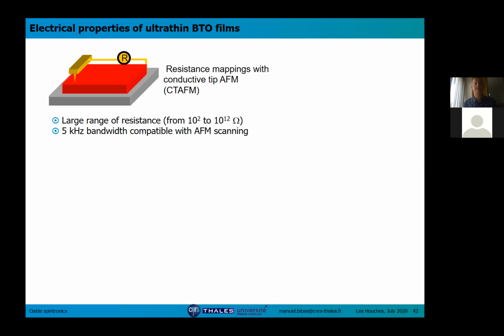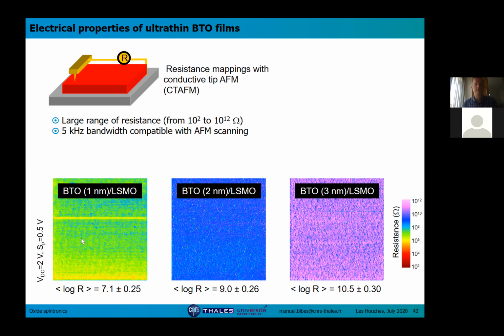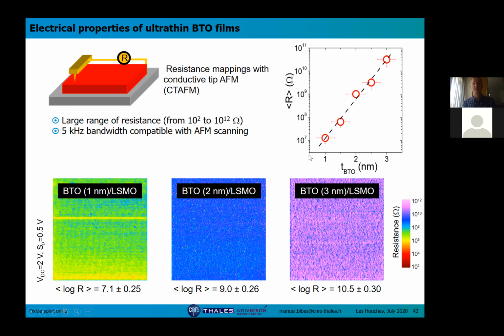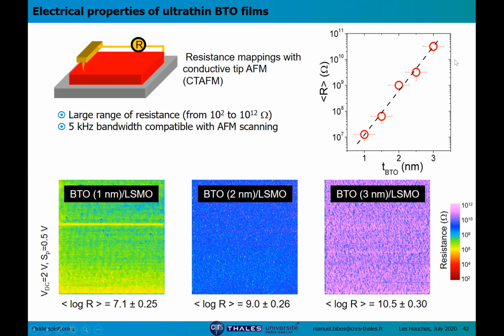Because these layers are very thin, we are also able to measure the tunneling current across them using an AFM tip. So we use conductive AFM. And here are the results in the virgin state for 1, 2, and 3 nanometers of barium titanate. You see that we have finite resistance values, and the resistance increases as we increase the thickness of barium titanate, and increases exponentially as we expect for tunneling. So these barium titanate films are good tunnel barriers, they're ferroelectric.